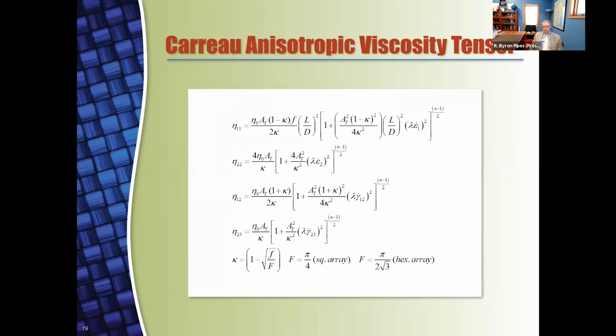The relationships are complex, but they are in fact analytic solutions to these properties, and they give us two extensional viscosities and two shearing viscosities that were developed earlier, with the idea that eta 2,2 and eta 3,3 were the same, and that 1,3 and 1,2 were the same. So there are actually three elongational viscosities and three shearing viscosities for such a fluid.